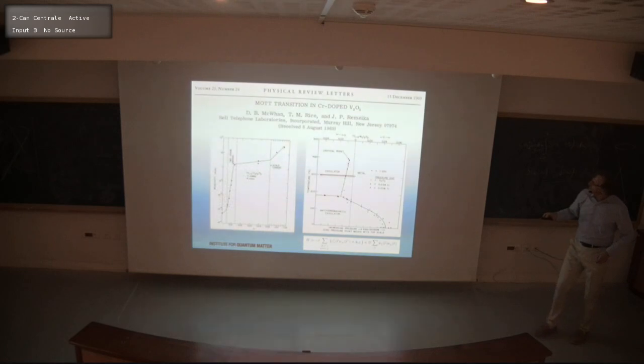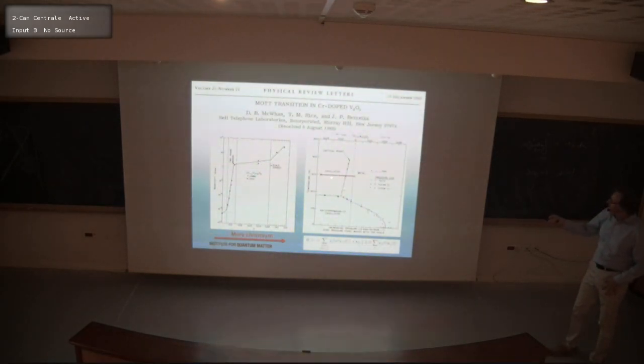Okay. The experimental evidence for it is actually a doping series. These are wonderful papers back from when I was a little kid, basically. So putting in chromium, you can really increase the resistivity by multiple orders of magnitude. It really is a marked thermodynamic feature, but you need to dope, and it's a whole sequence of samples. Okay, so we wanted to understand the nature of the state.